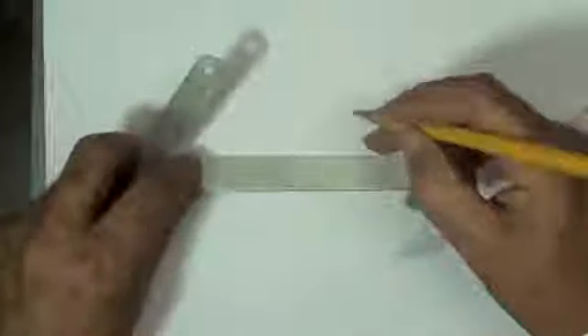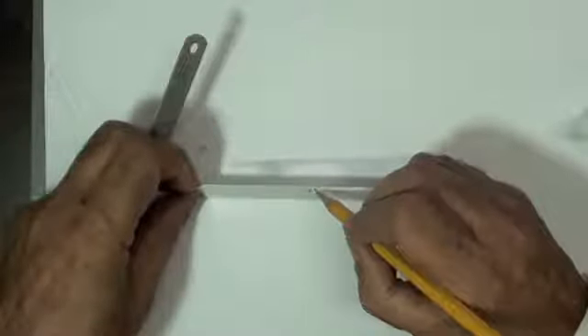Now, to align the strain gauge later, we'd like to have a reference mark. Usually there's a specific location where you want to accurately position your strain gauge. On aluminum materials, we can produce this mark by doing a burnish using a pencil lead. Now, you don't want to scratch the surface. You don't want to modify the surface or create a stress concentration. This would go against what you're trying to measure with the strain gauge. So we want to produce a mark on the surface that's visible but does not modify the surface, and that's the definition of a burnish.